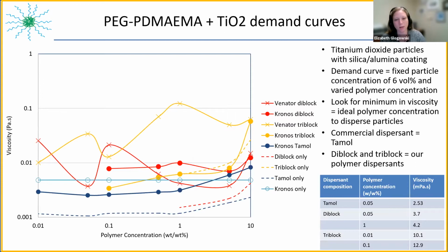So one test that we do to understand how well these polymers behave as dispersants for titanium dioxide is called the demand curve. So in the demand curve, we're testing the viscosity as a function of polymer concentration. So in this case, the particle concentration is fixed. So for these tests, the particle concentration is 6 volume percent, or about 20 weight percent. And then we vary the polymer concentration.